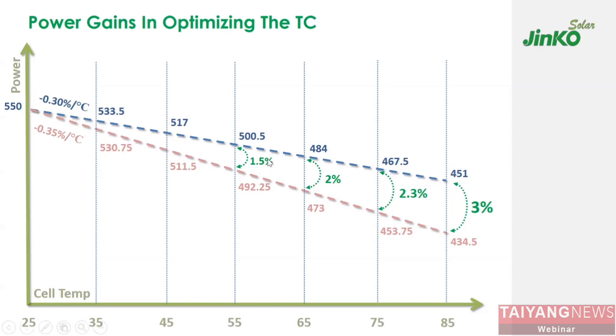And of course, maybe in some other areas like Northern Europe, Northern America, or Japan, the temperature coefficient is not significant, where the cell temperature may be between 35 and 45. But when we talk about Middle East and North Africa, we're talking about cell temperatures reaching 65 and even in some cases 75 and 80. So it's significant that you can have at least 2% of additional watt when you have only one factor contributing to this huge improvement in performance. We did not even consider the bifacial factor, the degradation, or the low light performance. We are only talking about one factor contributing to this.